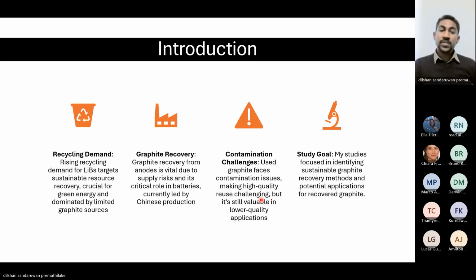So due to these reasons, the graphite recovery, or recycling of graphite from these lithium-ion batteries, needs to be addressed. But currently it's largely overlooked because of the lower economic value of this secondary graphite. There are other problems as well, like contamination challenges, because the graphite, when we take it out from the lithium-ion battery anode, is mainly contaminated by the electrolyte, maybe some metals from the cathode material, and it's also subjected to deformities because of the continuous charge and discharge cycles. So due to all these reasons, graphite that we can find at the end of the lifetime of lithium-ion batteries is going to be of very poor quality.